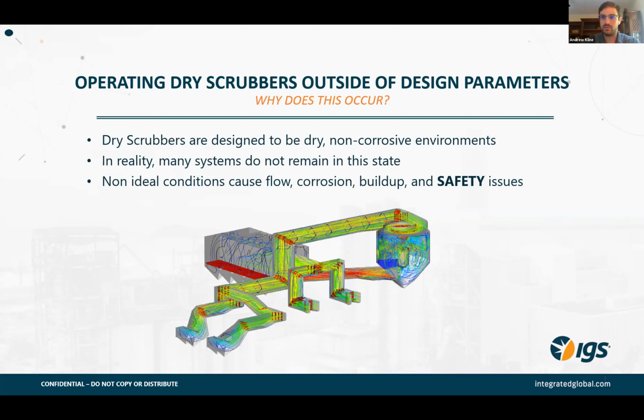And what we've seen is there's some units that always had corrosion issues that were well known and documented, and they knew they had to deal with them. But on the flip side, we've seen more and more units that have been periodically checking to make sure that they have wall thickness and aren't experiencing loss. And then all of a sudden, this last check, they had a dramatic loss in wall thickness. And I think that's really in part due to the cycled and low loading conditions. It allows us to get closer to the acid dew point temperatures, and also different flow parameters allow flows not to be uniform. Wetting can occur in one area. Overspray might be happening because of the flow discrepancies and things like that.